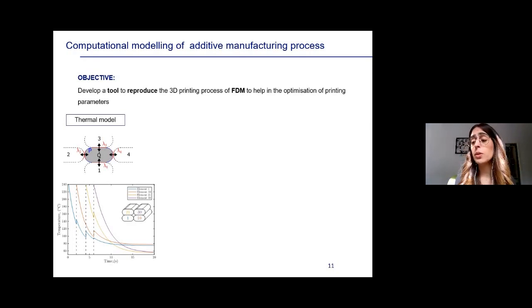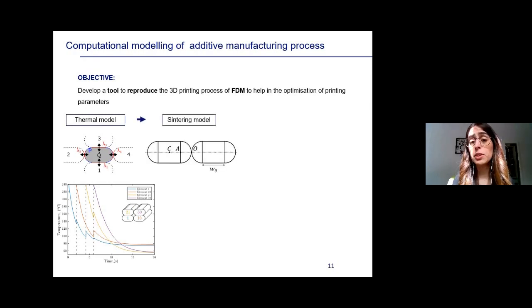We proposed this thermal model because the temperature history of the filaments during the 3D printing has a great influence on the final quality of the bond that is achieved between adjacent filaments. The second thing that we did was propose a sintering model. Sintering is defined as the coalescence of particles under the action of surface tension, and this model allows us to reproduce the bonding process that takes place between 2 adjacent filaments during the 3D printing.